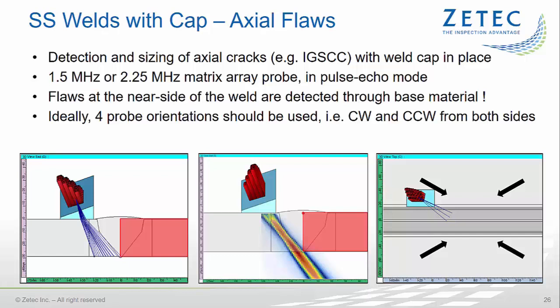As indicated on the images on this slide, the operator should not rely on signals that seem to originate from the far side of the weld. Ideally, the weld should be inspected with 4 beam orientations, so 2 symmetrical wedge assemblies are required to examine from opposite directions, clockwise and counterclockwise.